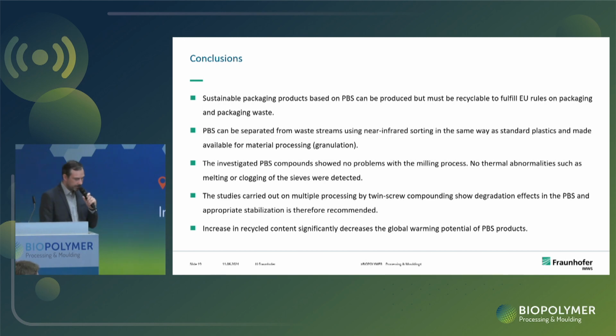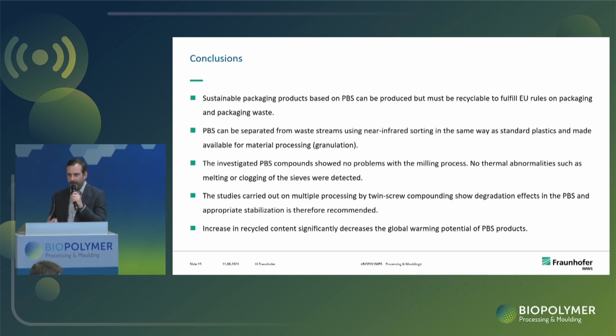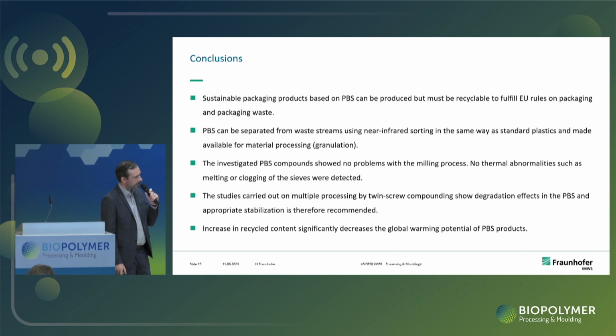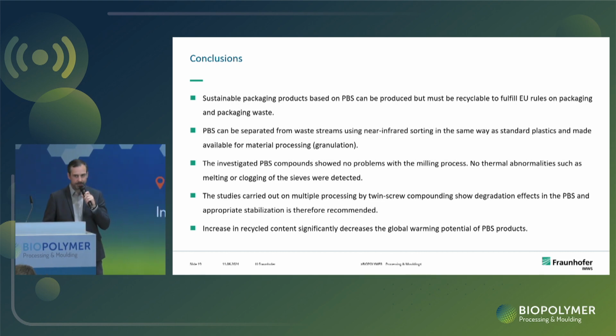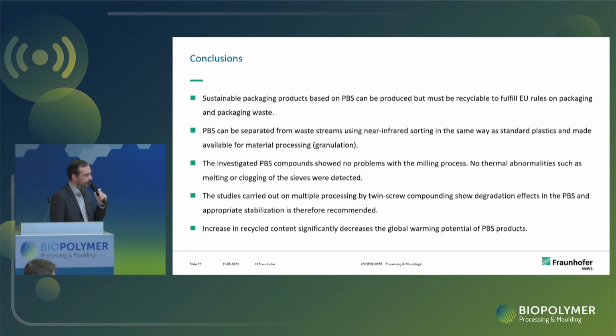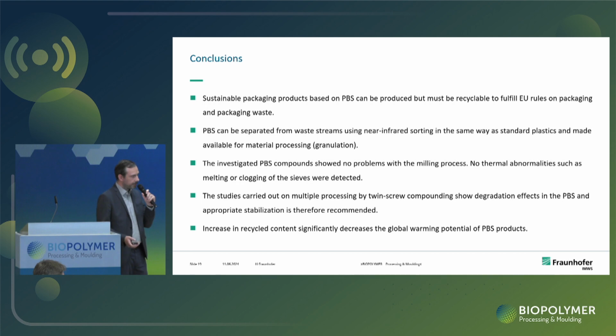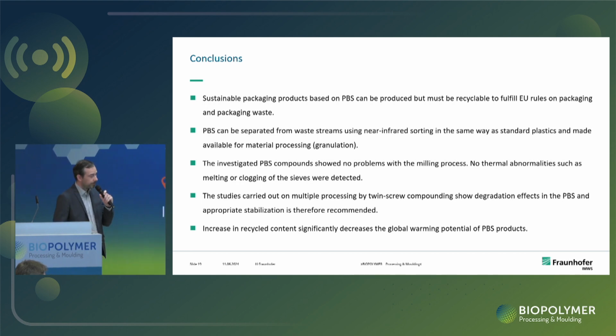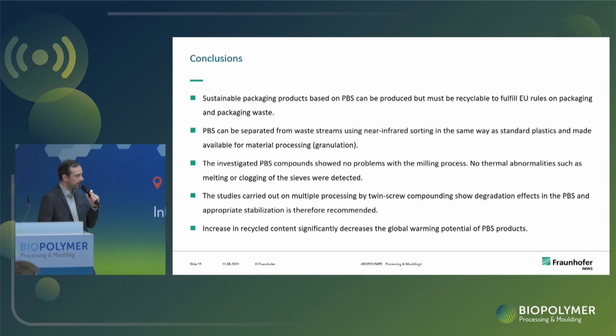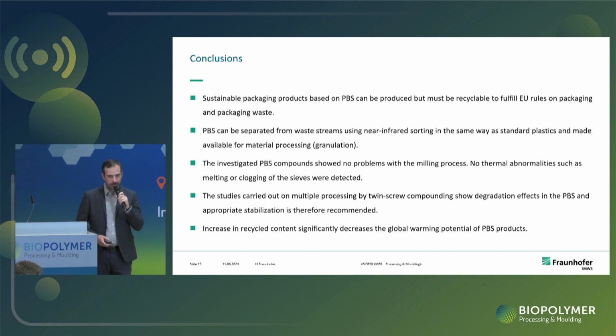Good. To summarize and give the conclusions and take-home messages: we think that PBS is a bio-based material which can be used to produce packaging. We show that PBS can be sorted out, separated from conventional plastics with conventional sorting technologies, and can also be granulated afterwards. PBS should be modified to stabilize it against the degradation effects we found in our processing experiments. And if you use more recycled material in your compound, you can significantly improve the carbon footprint of your material.